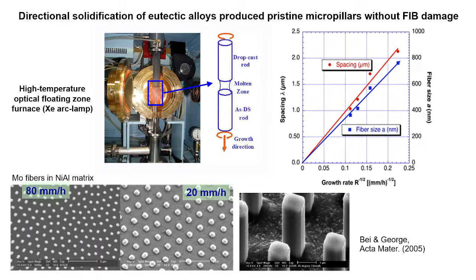And the nice thing about this system was that NiAl reacts only to acids and molybdenum only reacts to bases, right? So you can selectively etch the matrix from the fiber, and when you etch it, you end up leaving behind these perfectly pristine molybdenum fibers or pillars, right? And the nice thing about this is, because you don't have FIBbing, there's no FIB damage involved in it. In principle, you should have pillars with no dislocations in them.